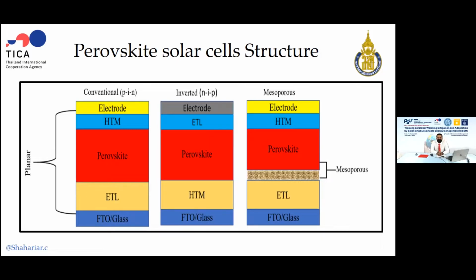Currently, it's under research due to the stability issue, because some researchers reported stability of perovskite of about 3 months, or some of them say 500 hours. The point is that if we compare with other solar cells, perovskite is cheaper, and it's also environmentally friendly. But due to the stability issue, it's still under research.